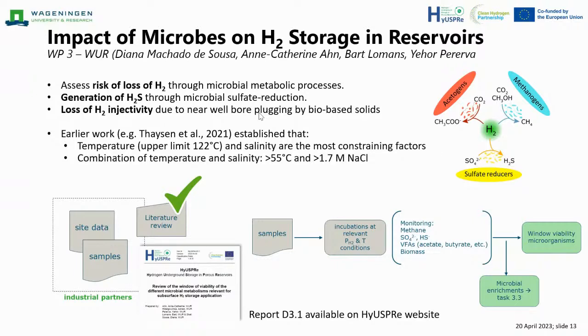Of course, potentially leading to generation of H2S in the case of sulfate reducers through microbial sulfate reduction, and also loss of injectivity due to near-wellbore plugging by bio-based solids from the growth of these microbes, excessive growth, I should say. Yeah, this basically builds on earlier work from Thaysen et al.